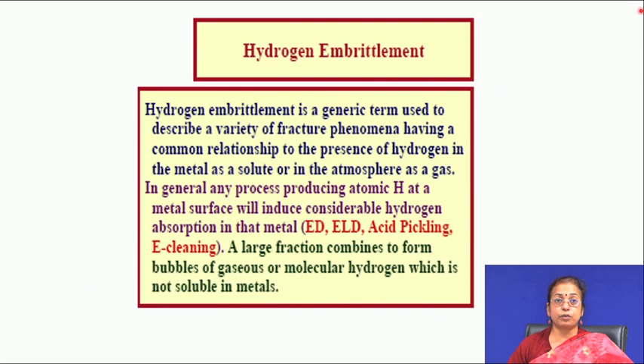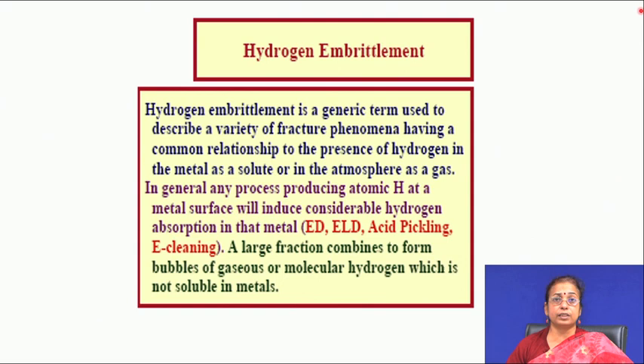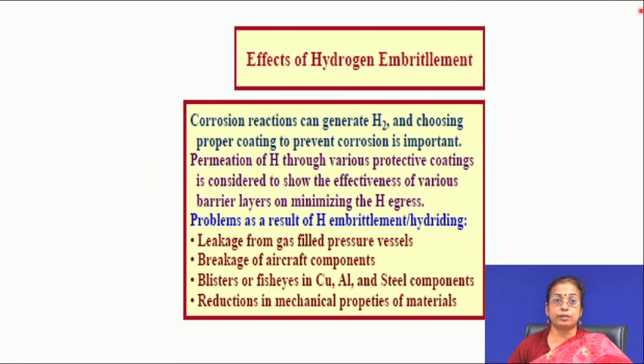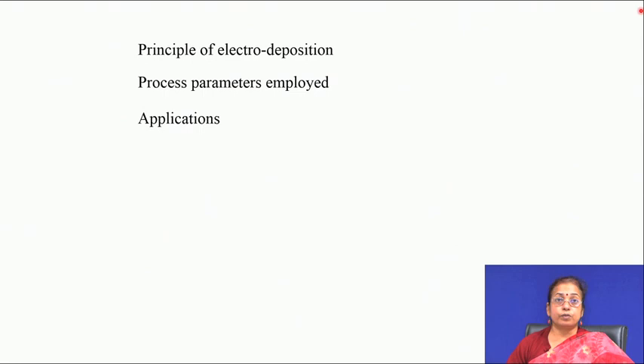One important process that plays a key role in both electro deposition and electroless deposition is hydrogen evolution. Hydrogen evolution is a competitive process — in the cathode there is hydrogen evolution as well. Atomic hydrogen may diffuse into the material. If you want to get rid of this hydrogen you can carry out an annealing operation. In this lecture we discussed electro deposition as well as electroless deposition, and also chemical conversion and electrochemical conversion processes.